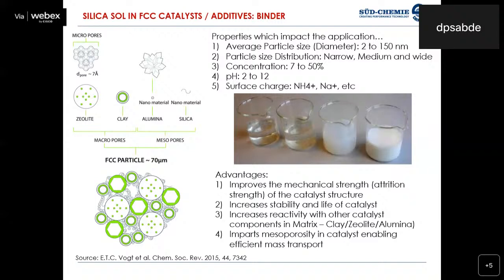So if you look at what kind of advantages it actually gives to the catalyst, basically it improves the mechanical strength. In technical terms, this strength is measured as the attrition index. Typically, most of these additives have an attrition index of less than 6, and silica plays a very important role in achieving the desired attrition in the catalyst. Of course, this also has implications for increasing the stability and life of the catalyst.